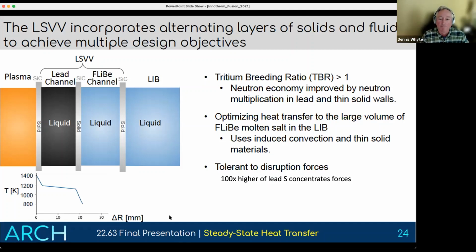So every solid surface basically keeps adding to the delta T from the plasma surfaces all the way over to the liquid immersion blanket. So the idea of this was basically to get rid of more solid materials, with the idea that we would try to have induced convective flow, particularly of the lead, that would enhance the heat transfer. The other challenge, which the lead was primarily there for, is that another challenge in fusion designs is that there's large electromagnetic loading, which is possible because of the large currents, forces, and stored energy in the plasma. And because the lead has 100 times higher electrical conductivity, basically all the structural forces get concentrated in the lead, which is good because it can't break.